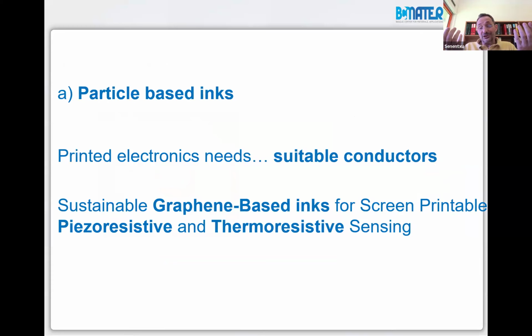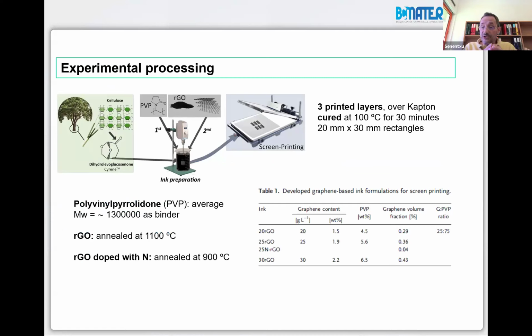And printed electronics always need conductors. If possible, the same system can be a conductor and also be used as a sensor and actuator. One of the most sustainable inks we have for conductors are graphene-based inks, okay, or other carbonaceous fillers. First of all, they are carbonaceous fillers, okay? They come out of carbon. They provide conductivity, okay? And for example, we can use more or less sustainable polymers like polyvinyl pyrrolidone, okay? With, for example, a solvent that directly comes from cellulose, okay? We have more or less sustainability in the solvent, more or less sustainability in the polymer, and more or less sustainability by using a carbonaceous filler that in principle has not so many problems, and other fillers that we can use, okay?